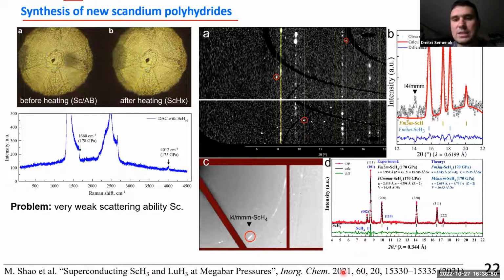But at high pressure it demonstrates some superconducting properties, and the results published in Inorganic Chemistry in 2021 show that there is one unexplained peak. It's in picture B on the right side of my slide. There is an I4/mmm sign, which shows one additional unexplained peak. And really, in our experiment, we also synthesized something with a similar X-ray diffraction pattern. We can see this small peak here. And of course, the main product is scandium H3.